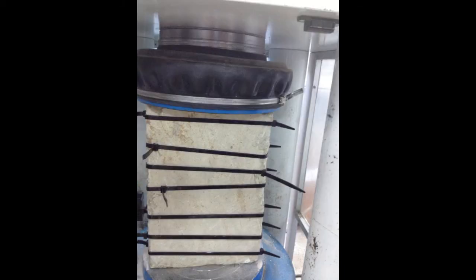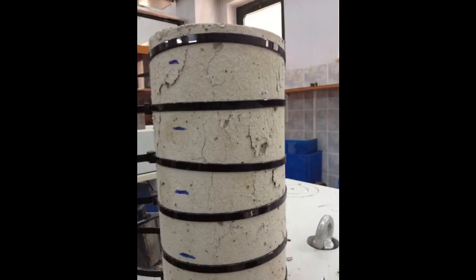When post-peak load test specimens with polyamide ties were loaded, a high tensile strain of the plastic ties and deformation of crack surfaces until tie failure could be clearly seen by the naked eye. Therefore, the polyamide ties were found to significantly change the deformation characteristics and increase the ductility of specimens in post-peak load tests. It should be noted that most failures of plastic ties were seen to occur at the locking parts of the ties.